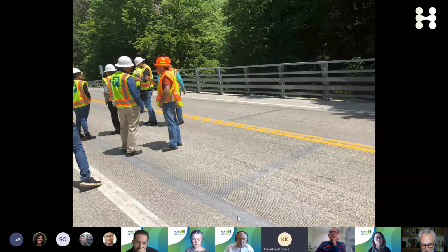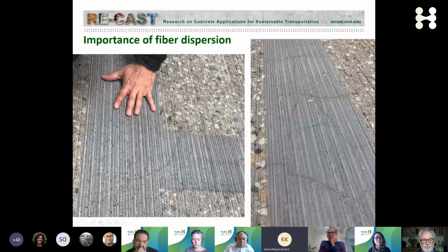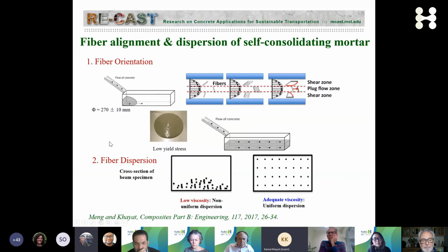And this is a bridge inspection I was at last year or 2 years ago in New York DOT, and this is the concrete that was done using UHPC. And I noticed something very interesting. We have some cracks, and this is mainly because of autogenous shrinkage, but you don't have any signs of corrosion. And where there are no cracks, you see some pit corrosion very, very close to the surface, meaning that the fibers are at the surface.